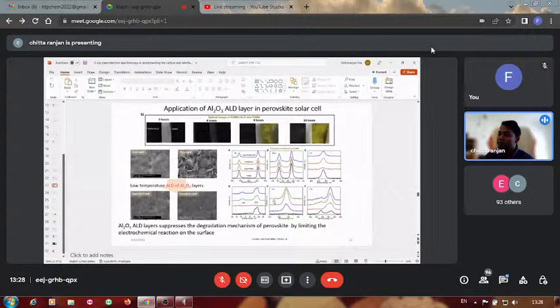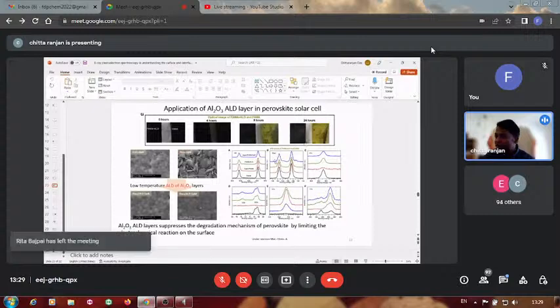We also did some other things, like putting on aluminum oxide using ALD. ALD is a very low temperature process, one can even use it at room temperature. So that's why it's good for perovskite materials, to protect against oxygen, air and water. Then we put on a few layers of ALD, and over time the one without ALD is turning yellow, and the other with ALD is not turning yellow, so it's still keeping the black or brown phase. And from here you can see the nitrogen spectra of this material and the nitrogen spectra of this one.